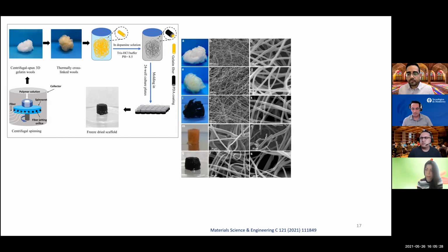If that's the case, that you want to modulate the diameter of the fibers, were you looking for a smaller diameter, greater diameter, below a certain range, below certain microns, or what would you be looking for? Undoubtedly, we are looking for a smaller diameter for the fibers, because with electrospinning it's possible to produce real nanofibers, less than around 100 nanometers. However, with centrifugal spinning, most of the time the smaller diameter that we could synthesize was about 200 to 300 nanometers. So we need to produce fibers with smaller diameters.